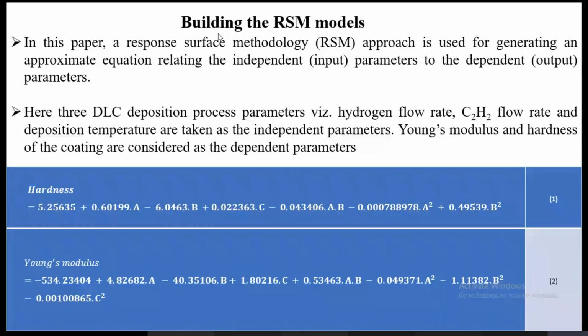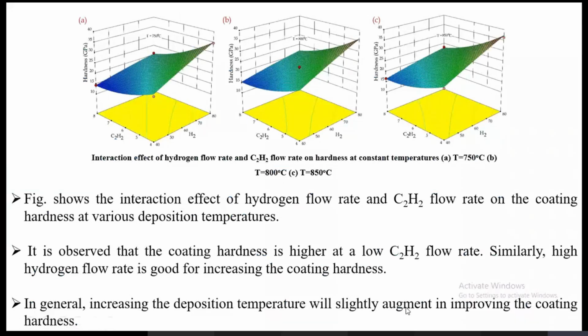So in the RSM model, one equation was developed for each response parameter by considering three input parameters: the hydrogen flow rate, the C2H2 flow rate, and the temperature. For these two output parameters, these two equations were there. Now these are some interaction plots, showing how the response parameters, like hardness or Young's modulus, change with respect to the input parameters, meaning which input parameter has the highest significance for the output parameter. That we also developed in this case.